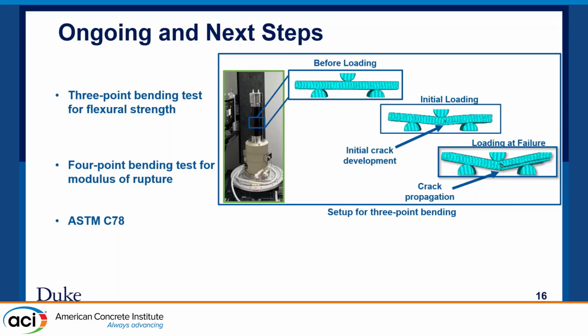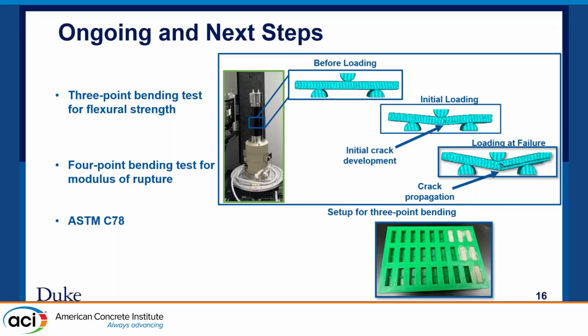With our machine, we can see the crack propagation with time while the specimen is being loaded. And this is just a practice test we did on a wood sample during our training. By this machine, we can see the crack propagation with time while the specimen is being loaded.